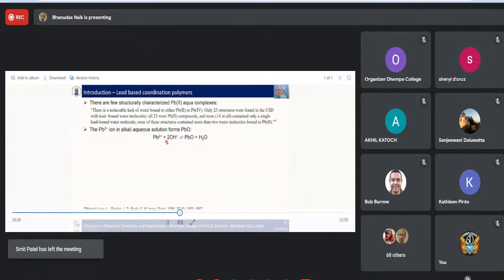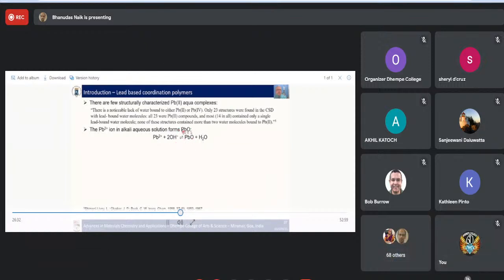The other thing you have to watch out for is the lead-2 ion. If you have a slightly basic solution, you form lead oxide, so you have an equilibrium between the two as well. This is really important. As I showed you before, you want to basify the solution to dissolve your ligand. But when you work with lead, you can't basify too much, otherwise you'll form lead oxide. So you have to have a sweet spot for the pH of the reaction.